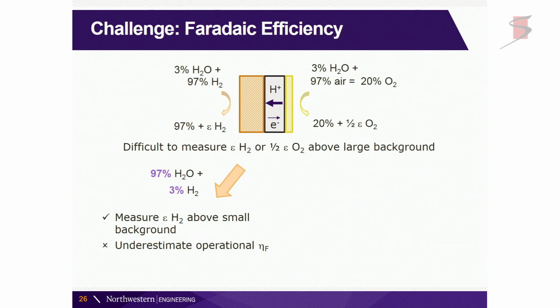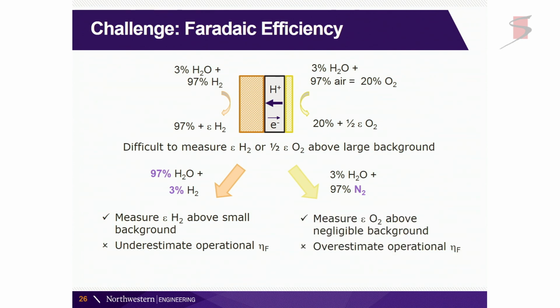On the other hand, you say, let me change what I'm supplying to my air electrode and move into something that is a little less oxidizing so that I can actually see the oxygen that's being produced. Okay, so that's good. I'm going to be able to measure over a small background, maybe negligible background, but now I'm going to overestimate the Faradaic efficiency because I've shifted my electrolyte into a regime where the electronic conductivity is much, much lower.